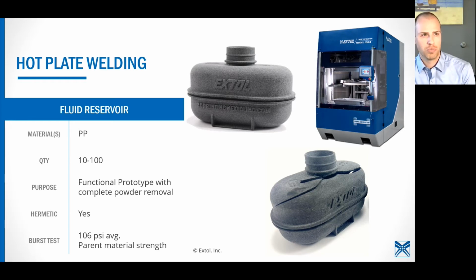We needed the functional prototype, but we couldn't print it in one piece because we needed to get the powder out of the inside. Often these types of reservoirs have different bevels or bellows on the inside that trap fluid in different areas or keep it from sloshing around. Those internal cavities would make it impossible to get the powder out. It needs to be made in two pieces. Again, we can produce a hermetic seal and achieve a burst strength that achieves the parent material.